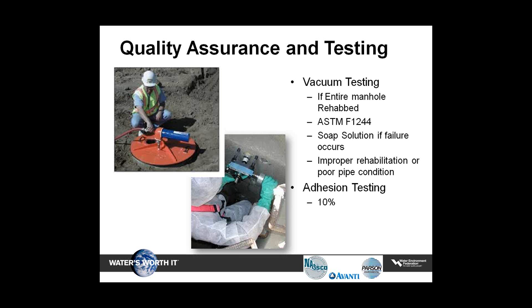If the inspector determines that the failure is due to improper rehabilitation, then the contractor shall repair according to the manufacturer recommendations and retest until a successful vacuum test is achieved. If the inspector determines that the failure was due to poor condition of the pipes or angular space between the pipe and the pipe liner, or the inability to seat plugs properly, and that there are no visible defects in the applied product, then it will be determined that the manhole has passed.